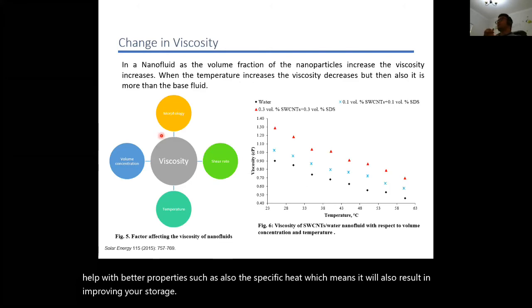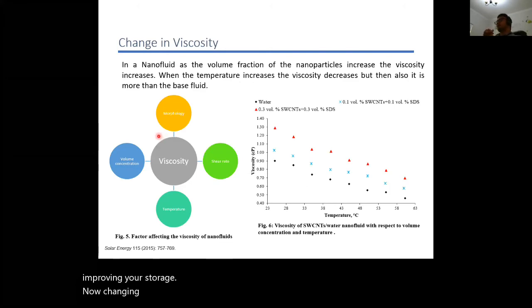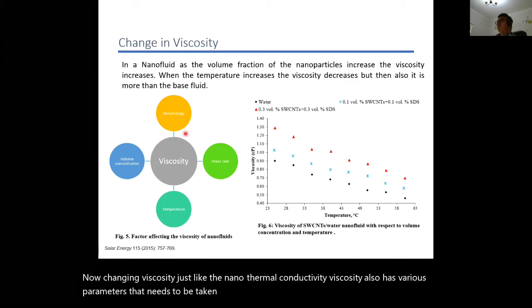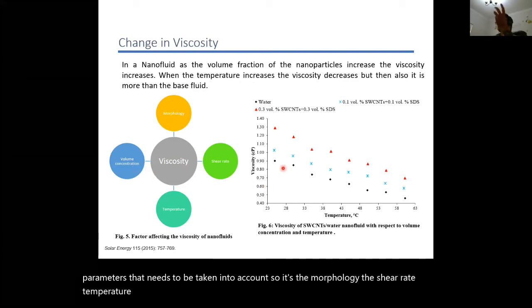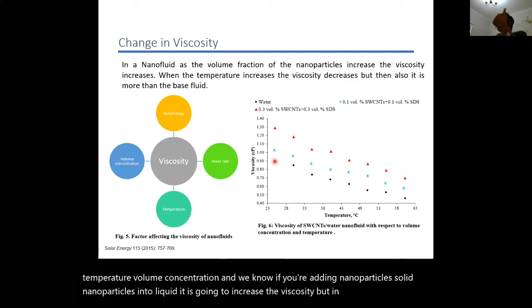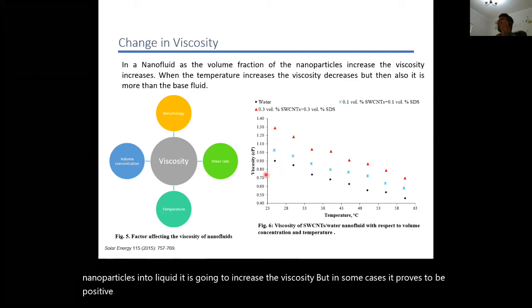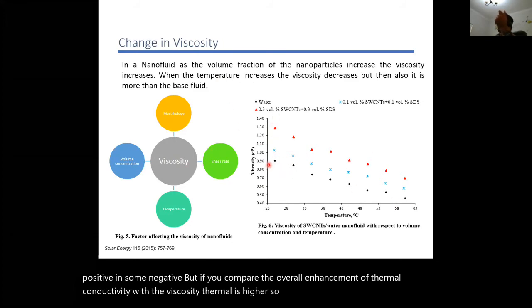Now, change in viscosity. Just like the nano thermal conductivity, viscosity also has various parameters that need to be taken into account: the morphology, the shear rate, temperature, volume concentration. And we know that adding solid nanoparticles into liquid is going to increase the viscosity. But in some cases it proves to be positive, in some negative. But if you compare the overall enhancement of thermal conductivity with the viscosity, thermal is higher. So usually this is neglected.